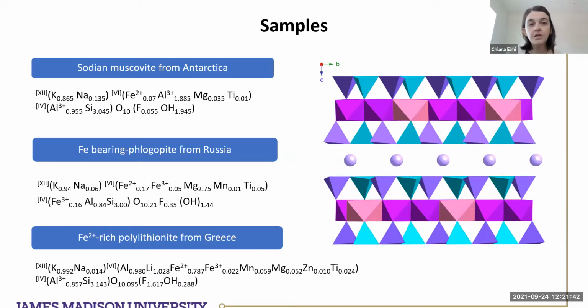So the samples that I considered in this study were the sodian muscovite from Antarctica, Fe bearing-phlogopite from Russia, and an iron-rich polylithionite from Greece. You see these long formulas with these nice little numbers here. This is a structural formula, so it puts together the information of the structure and the information of the chemistry that I collected with the single crystal for the structure and the microprobe for the chemistry. So based on this formula, you see also these Roman numbers. Those are the sites, so where these cations are sitting in the structure. So this is the coordination of the cation in the site.